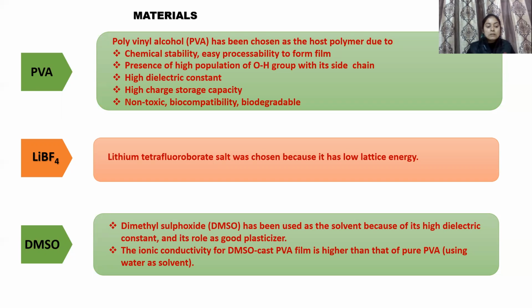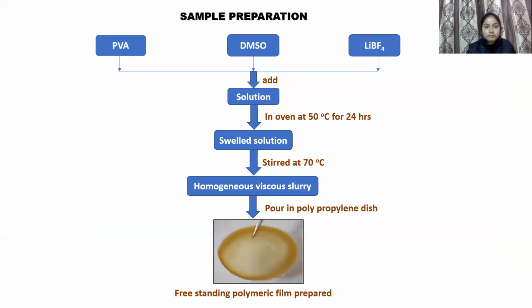sulfoxide. Now, in this work, we have used DMSO as solvent rather than water, because the ionic conductivity of DMSO cast PVA film is higher than that of pure PVA using water as the solvent. Now the sample preparation.